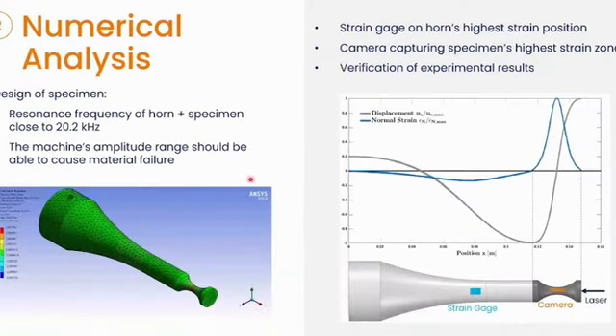So the first step of this procedure is a numerical analysis, so that the specimen can be designed to guarantee that the frequency of the system is around 20 kilohertz, and that the machine's amplitude range will be able to cause the failure.